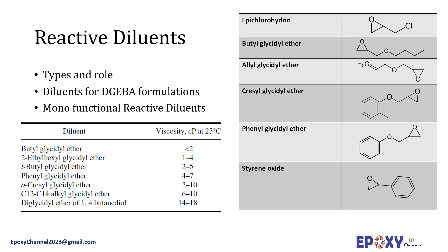The primary reactive diluents are mono-epoxy, low molecular weight epoxy resins. These may be used at rather high concentrations with little effect on cured properties. Often they are added to make selective improvements on certain properties such as adhesion, thermal cycling resistance, and impact strength. The monofunctional epoxy diluents are essentially chain stoppers, since they inhibit crosslinks from forming. The extent to which cured properties are affected is directly dependent on the concentration of diluent added. The general effect is to reduce viscosity and improve impact and thermal shock resistance, while slightly reducing thermal resistance. Monofunctional epoxy diluents are used primarily with diglycidyl ether epoxy blends; the most common are butyl glycidyl ether and phenyl glycidyl ether.